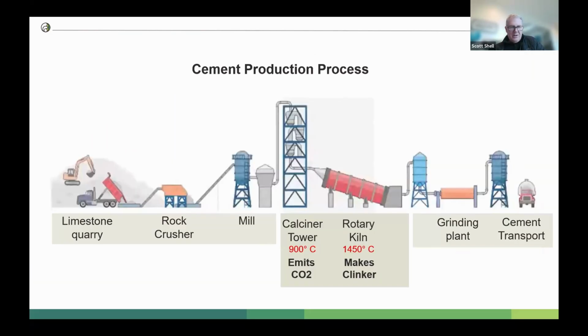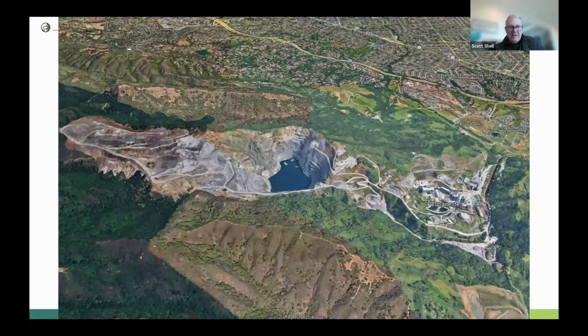So to make cement, you dig up limestone, you crush it, you mill it, you put it in a calciner tower and heat it up to about 900 degrees centigrade. That creates a calcination process, a chemical process that emits CO2. You then put that in a rotary kiln at 1450 degrees C, and that makes clinker. You grind up that clinker, and that makes cement. So here is that process in photos.